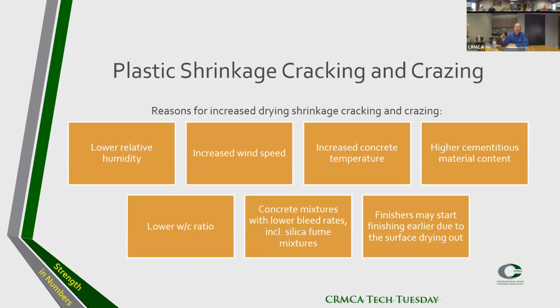Reasons for plastic shrinkage cracking and crazing: low relative humidity, so if it's dry, like we have here in Colorado, increased wind speed in the afternoon, increased concrete temperature. The higher the cementitious material content, the higher the potential for cracking and crazing. Even though we like to sell cement as a cement producer, we still recommend to lower the cement content generally in concrete to reduce the shrinkage cracking.